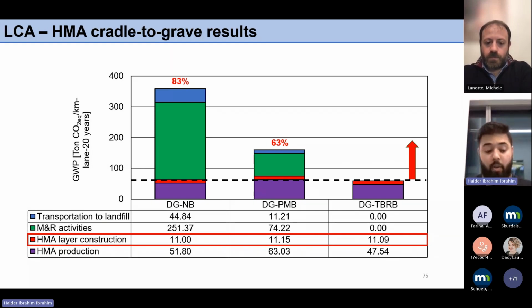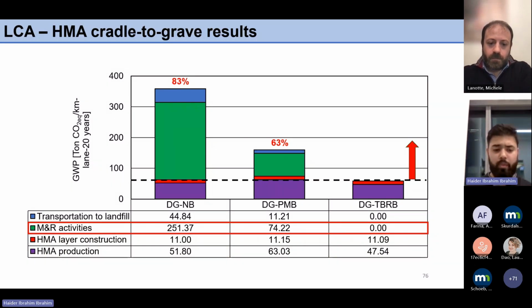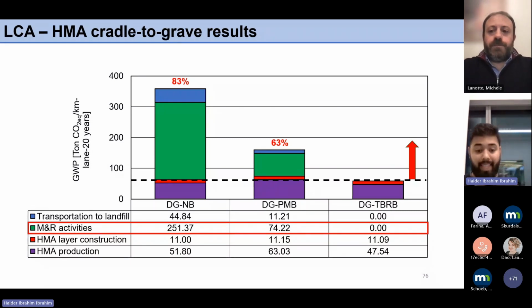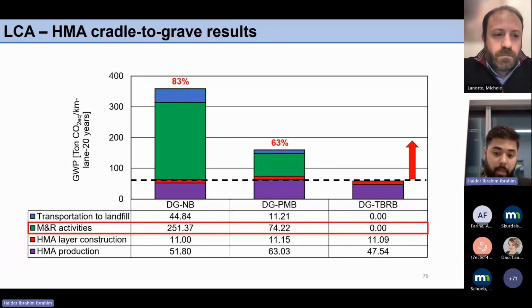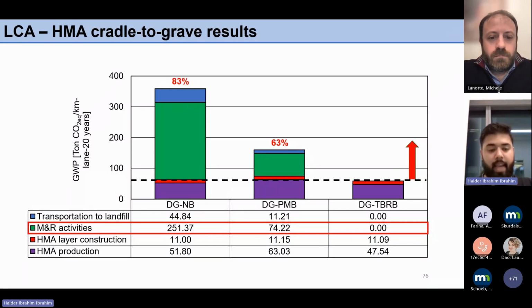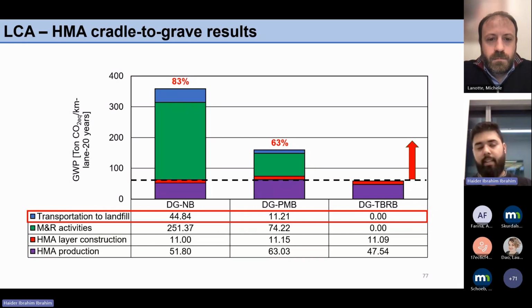The M&R activities now affect the DG neat bitumen the most, with a very high environmental burden because of the four reconstruction cycles, which includes obviously the production, the milling, the laying of asphalt. And the DGPMB also has that, but only for one reconstruction cycle. And of course, then there is the added burden due to transportation to the landfill, which in the DG neat bitumen case is a lot more than the DGPMB and the DGTBRB, since it was not milled and transported to the landfill facility in the service life, it's effectively zero.